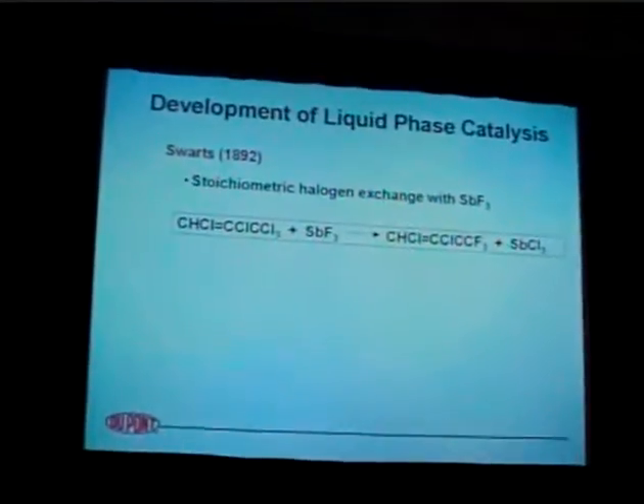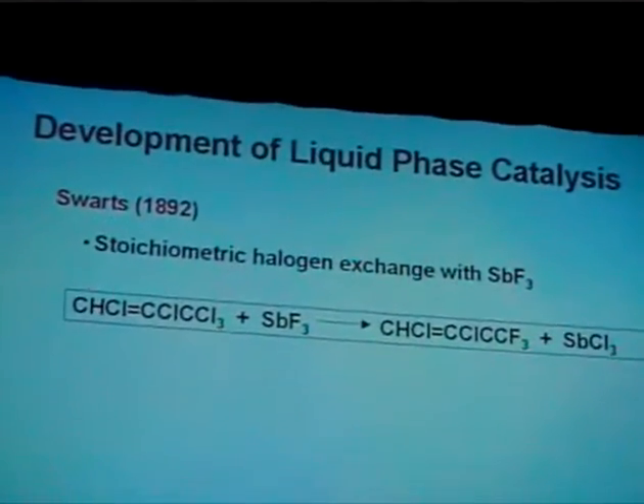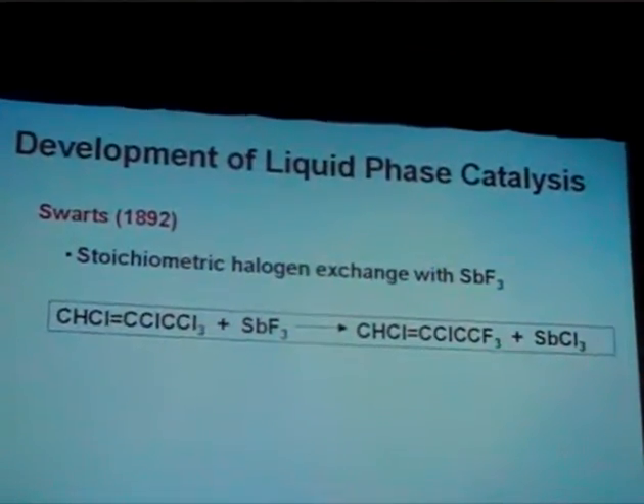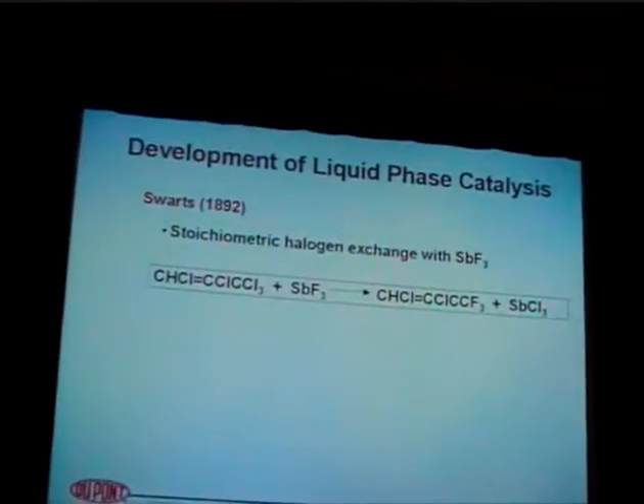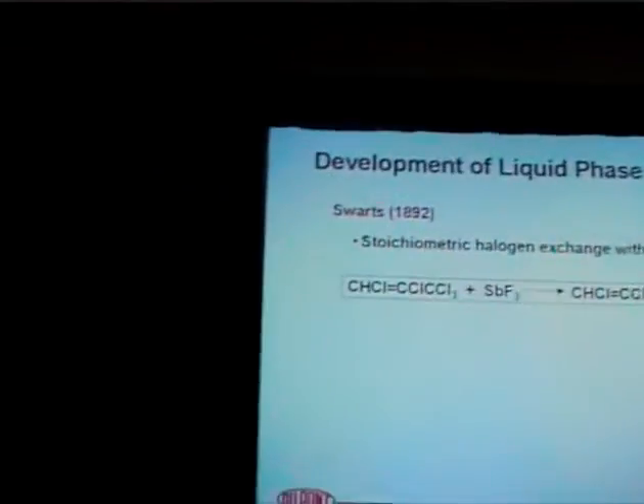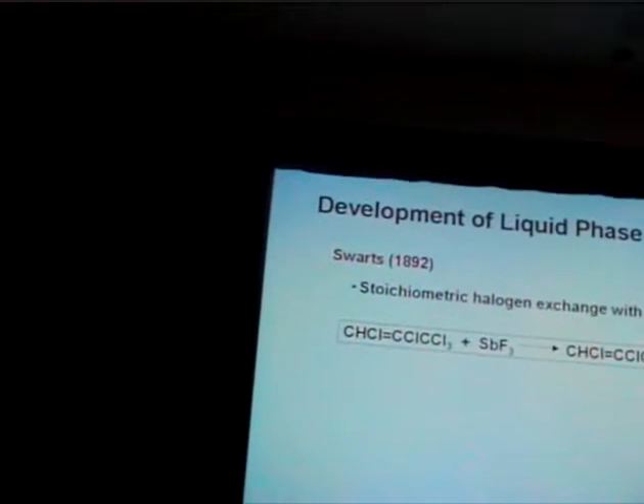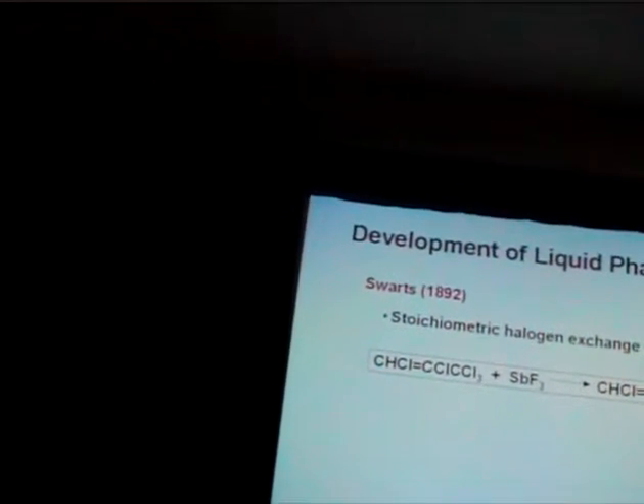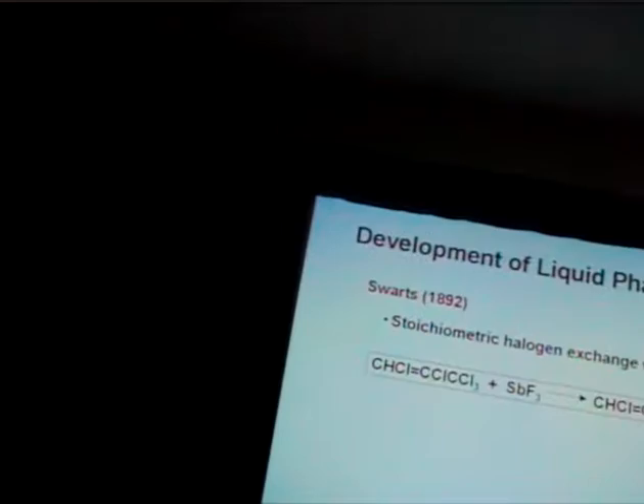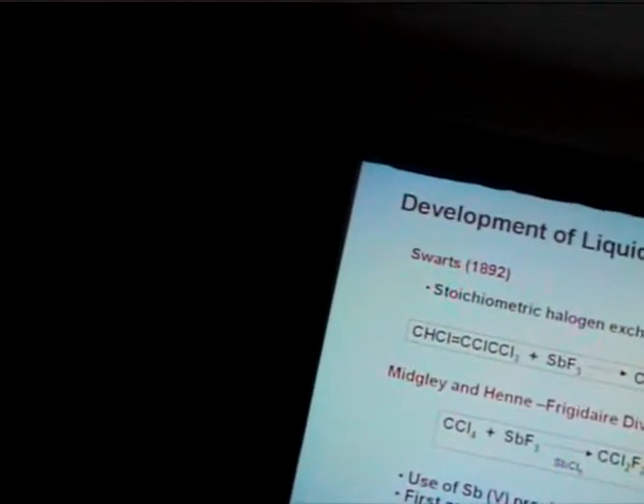So back in 1892, Frederick Swarts found that he could react activated carbon-chlorine bonds, such as that allylic CCl3 bond there, with antimony trifluoride to replace the carbon-chlorine bonds with fluorine to make the CF3 group there. It was not catalytic, it was stoichiometric chemistry, but it was the first synthesis of carbon-fluorine bonds. He evolved that chemistry nicely, but in